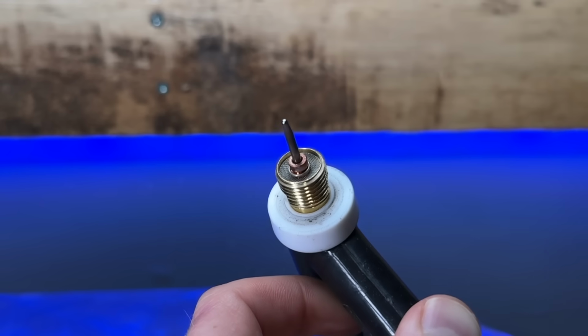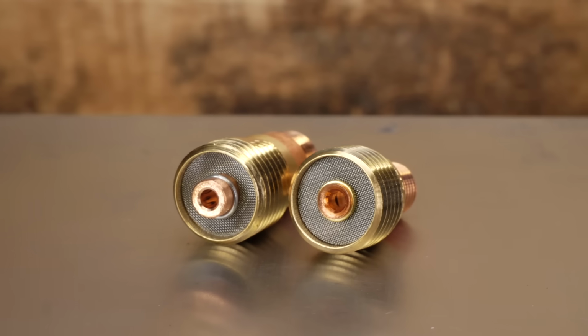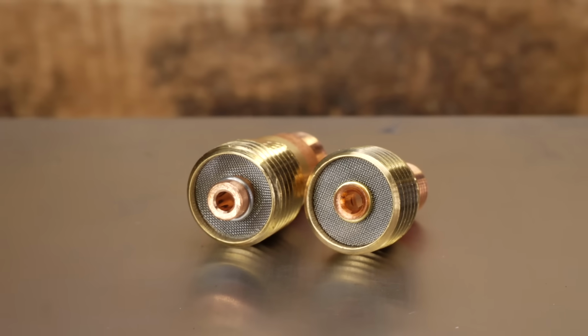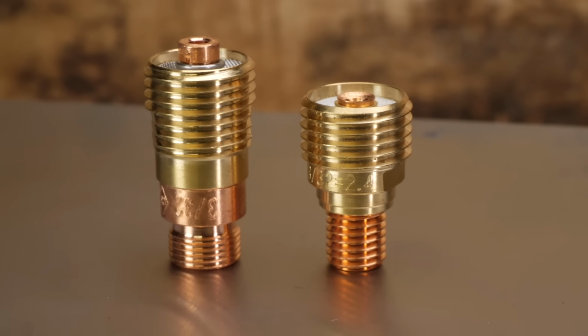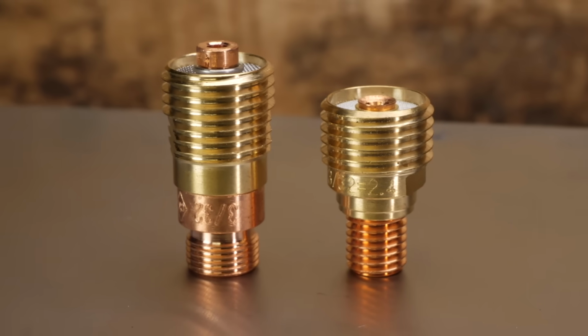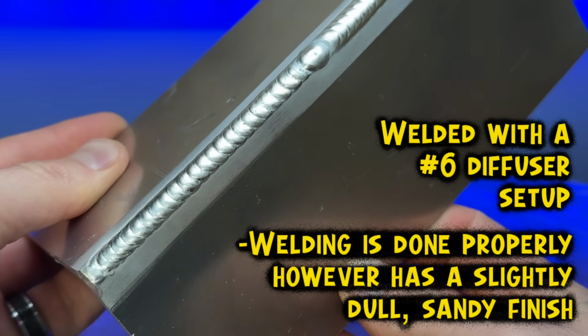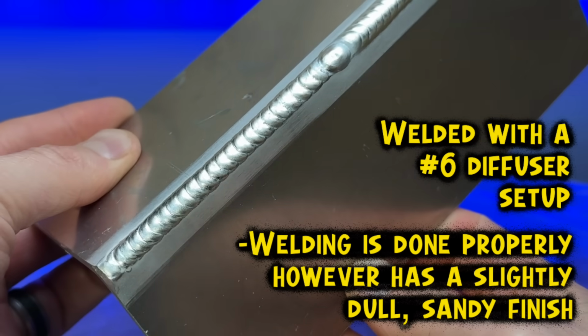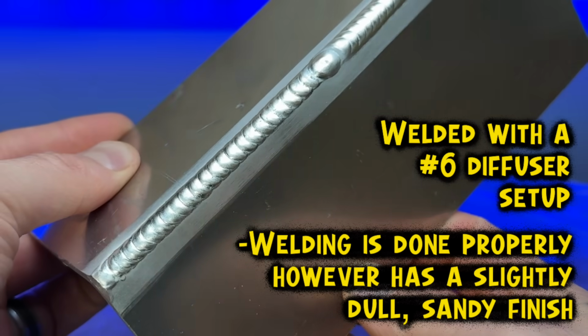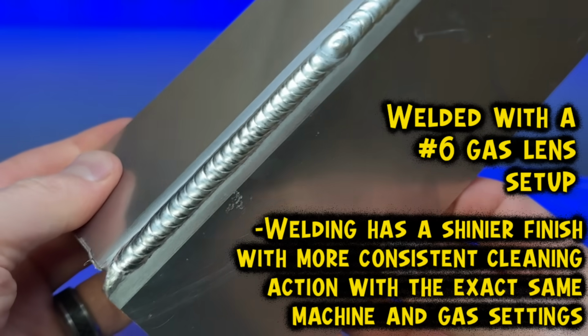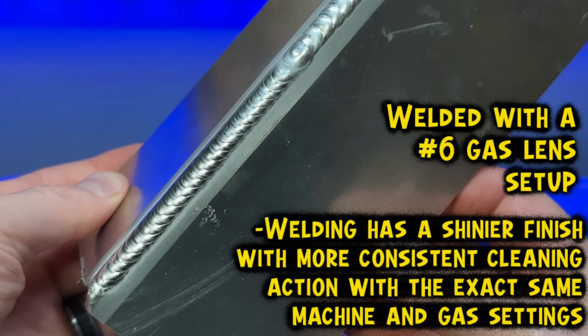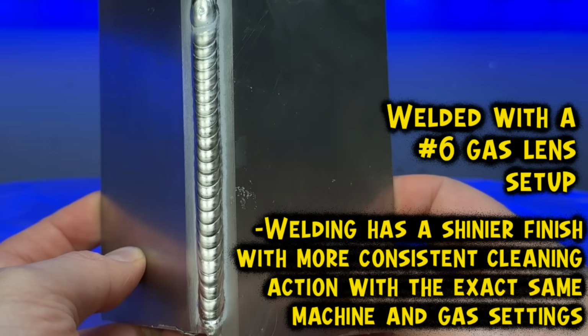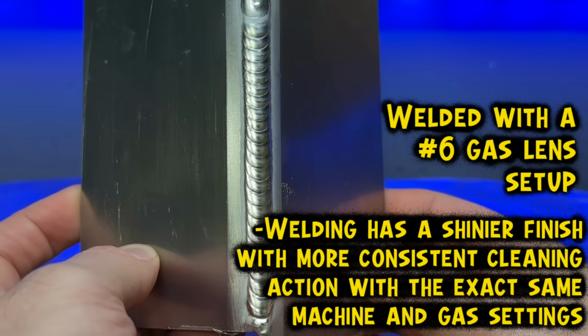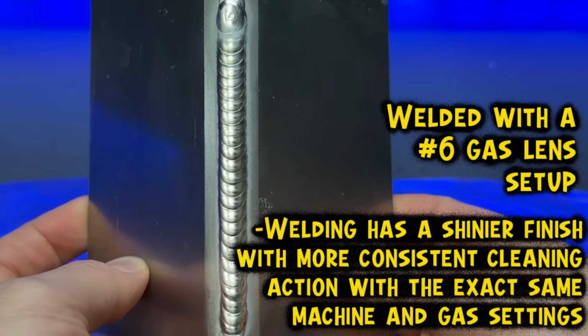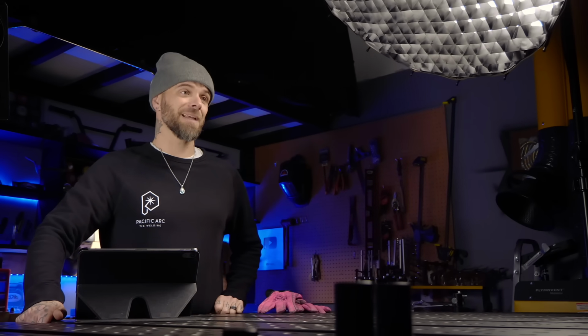I personally find that the gas distribution coming out through a screen in the gas lens is a lot more even and a lot more stable, especially going around shapes and outside corners and stuff like that. And when I'm doing something like an outside corner joint, I particularly notice a better coverage of gas when using something like a gas lens as opposed to a gas diffuser setup. I find that the gas lens and the screen inside of it provides a more even and smooth distribution of gas. And anytime that I'm welding aluminum, typically I'm going to probably use something like a number 6 cup.